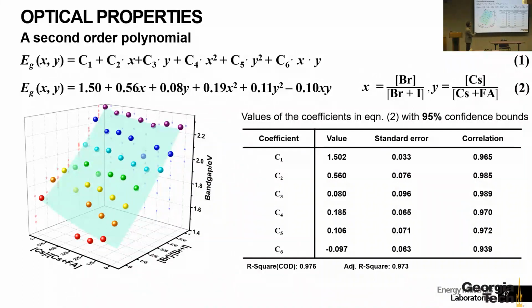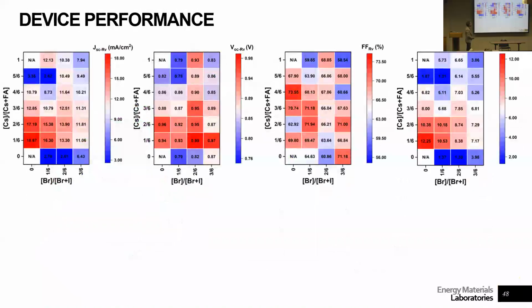Again, here, band gap, for example, so we measure the different band gaps. You can see from changing the bromine or changing the A site, we see different band gaps. So here's the band gap in the Y axis here, the Z axis. And then finally making devices, right? So we are able to make devices, measure the current, the voltage, the fill factor, and the power conversion efficiency. And here the red will be the highest efficiency. So, somebody is manually making these devices, not really optimizing every single step, but running through the standard recipe and making a lot of devices in one go. So with this study, I think we made something like 1,500 individual devices that were published last year.